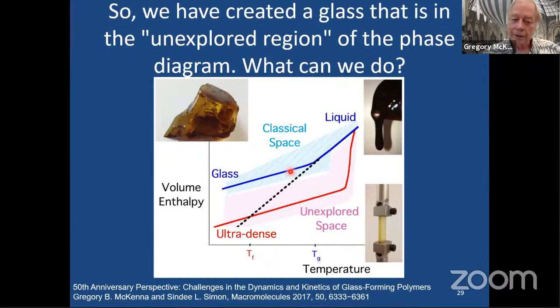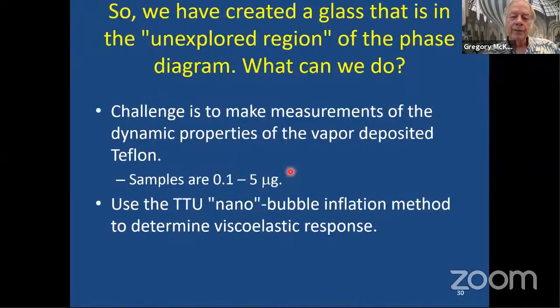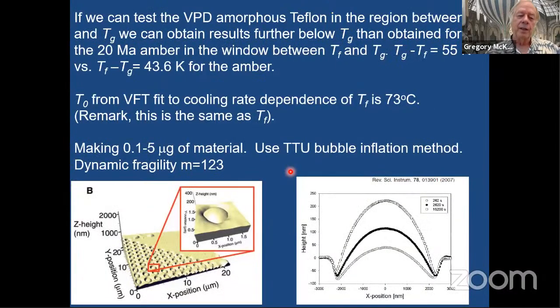So again, back to my ultra stable glass and the unexplored region that we're interested in. And so, like I said, the challenge is to make measurements of this vapor deposited glass. We only get 0.1 to 5 micrograms. And here's what the bubble inflation method works with. I just show that these are nano bubbles. These are micro bubbles. Actually, these are 1.2 microns in diameter, and we can go to 10 or 20 microns in diameter, and we can go down to as small as 3 nanometers. But here we were using a couple of 100 nanometer thick because we wanted bulk-like properties. But when we apply a pressure to the bubble, we watch it creep, and the creep gives us information about the dynamics.